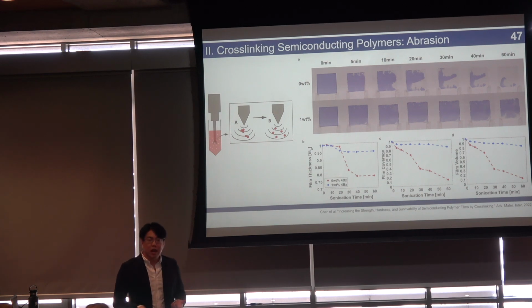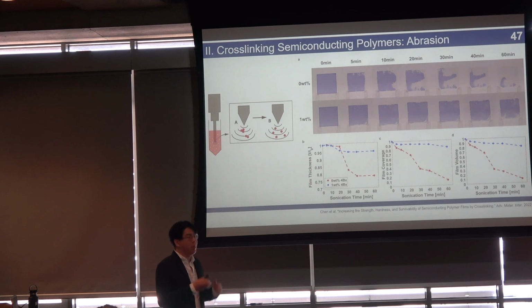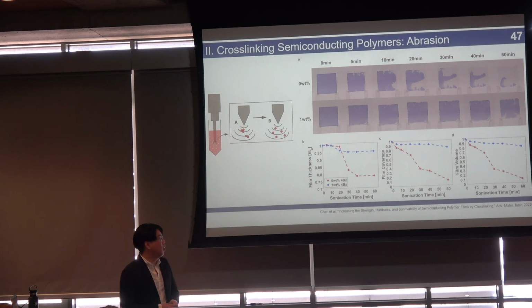And with some image analysis and some UV-vis spectroscopy, we can approximate the film volume that's remaining. And we see that for a non-cross-linked film, we have less than 10% of the film remaining, whereas for a cross-linked film, we have over 85%.